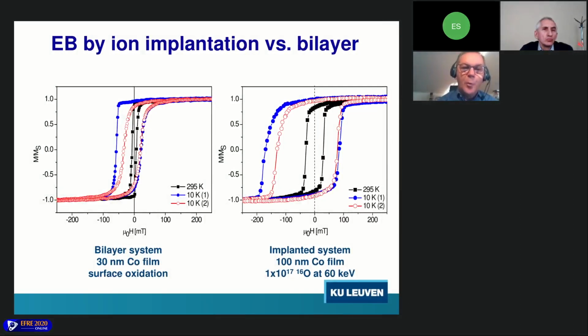We're going to compare the exchange bias on the bilayer. This is the picture that you have seen before, and we're going to compare this here with the exchange bias effect on our ion implanted system. Please note that the field scales are exactly the same, but you see that the hysteresis loop in our ion implanted system is really much broader. So this ion implantation leads to a really radical modification of the magnetic properties, and we have an exchange bias effect that is several times larger than what has been observed before.